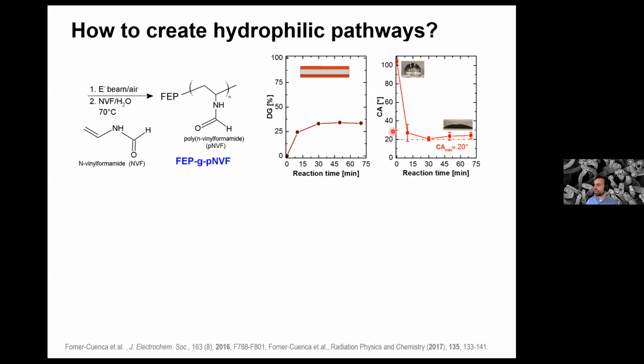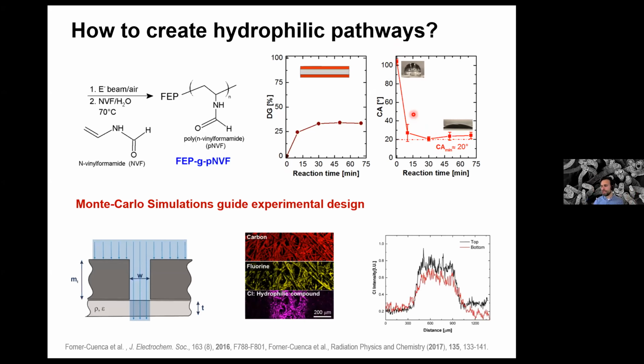And after a very short time, only 10 minutes, you have already decreased your contact angle that was initially 100 degrees all the way down to about 20. So you turn a very hydrophobic surface into a very hydrophilic surface. And then we looked at how the patterns look like. So remember that we irradiate from the top, and then there are these masks. And this gray area here is the GDE.